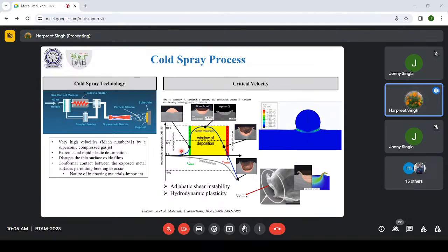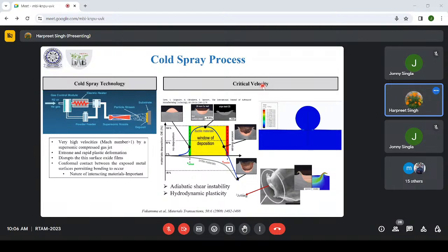Now, when you say velocity, it's not that you will propel the particles and they will stick on the surface at any velocity. What that means is that we have some critical velocity for the particle, only then will we get the deposition. Otherwise, deposition will not happen. This is a nice diagram which is shown here.